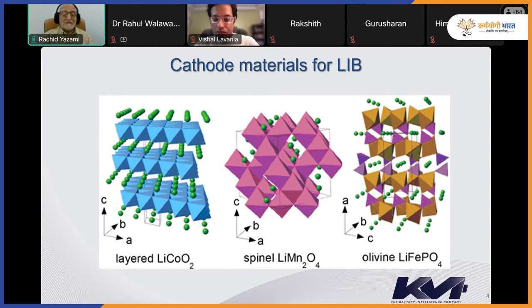The interesting thing is that the oxide slab, the blue structure, is very, very stable. It's a sandwich of the metal, which can be cobalt, nickel, or manganese, surrounded by two layers of oxygen. That makes the metal oxide MO2 slab. And between the slabs, lithium can move very freely and rapidly between the layers, enabling the charge and discharge of the battery. The other structure is called the spinel structure. It's a cubic structure, and the typical one is lithium manganese spinel, LiMn2O4. Some substitution of manganese with other metals like nickel or cobalt has already been tested, and it works quite well.